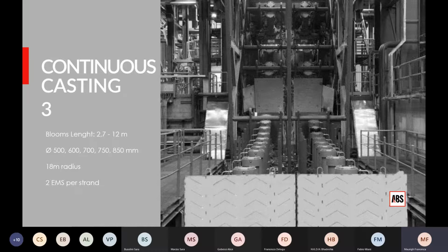It can cast blooms starting from 500, which means half a meter, up to 850 millimeter. It's a curved continuous casting machine with a radius of 18 meters, so really big. It has 2 electromagnetic stirrers per strand, and it has allowed ABS to replace a significant amount of ingots as a starting product to roll very big rolled bars, but also as a starting product to be directly sold to our customers for hot forging applications, such as ring rolling and open die forging of really very large products.